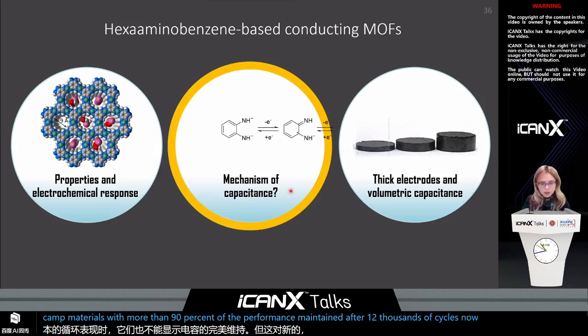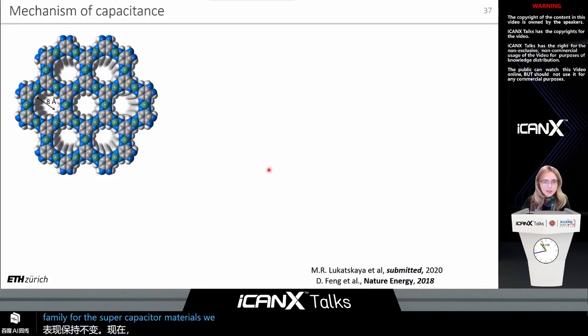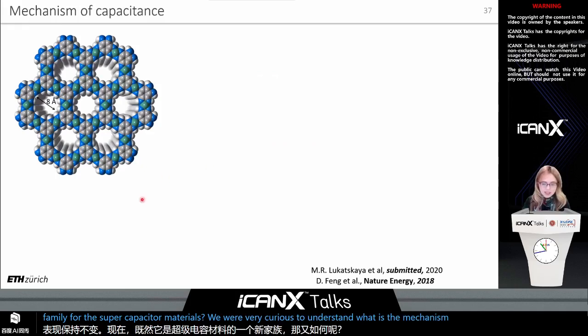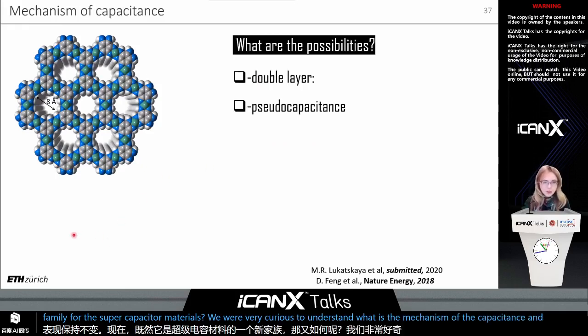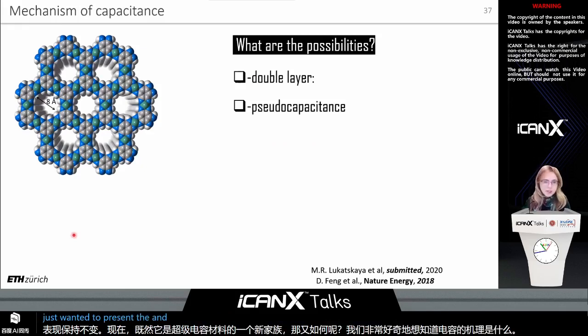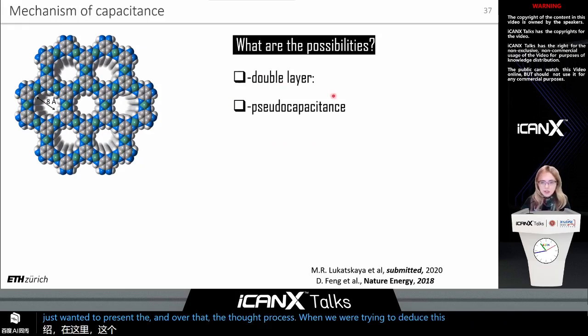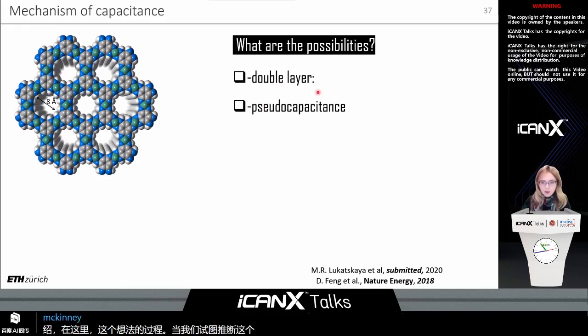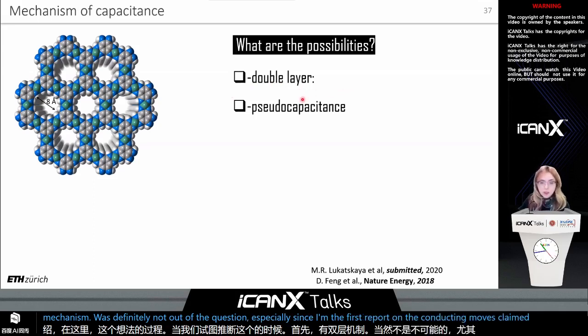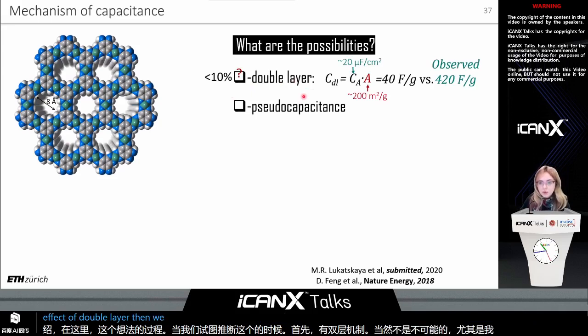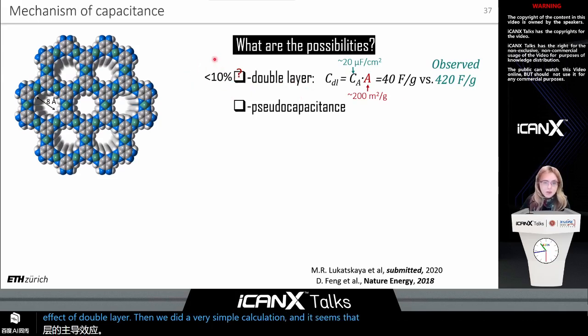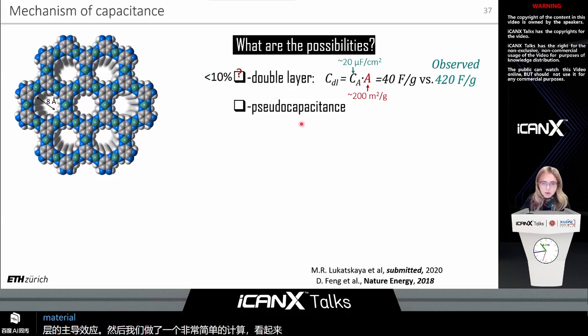Now, since it's a new family for the supercapacitor materials, we were very curious to understand what is the mechanism of the capacitance. And here I just wanted to present the thought process when we were trying to deduce this. So first, the double layer mechanism was definitely not out of the question, especially since the first report on the conducting MOFs claimed the dominant effect of double layer. But then we did a very simple calculation, and it seems that with the specific surface area that we have for this material, less than 10% is expected to be related to double layer response.